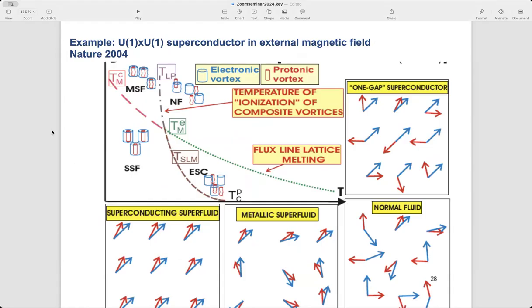This is the schematic phase diagram which was in this Nature paper. A trivial phase transition is, let's say, from a vortex lattice, and then you apply a temperature, considering a system with finite temperature. In principle, one of the processes that could happen is you can melt, let's say, the protonic sublattice. You can tear smaller fractions away from higher fractions and melt it, and then basically there would be a lattice of only vortices carrying a larger fraction of the flux quantum, and then a liquid of vortices carrying a smaller fraction. And in that case, you disorder one of the condensates, but the other condensate stays ordered.